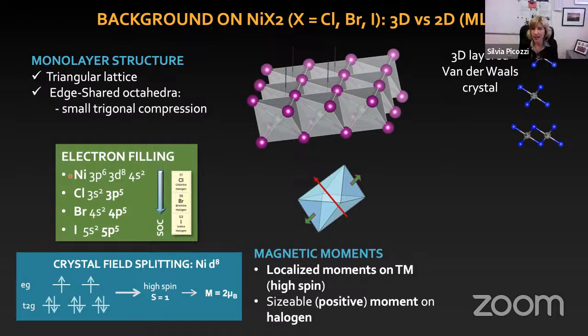And so nickel is d8, and I have an octahedral crystal field, so I have the t2g fully filled and the eg half filled. So I have 2 Bohr magnetons per nickel atom. And then if I move from nickel chloride to nickel bromide to nickel iodide, I'll see my spin-orbit coupling increases. So I expect larger spin-orbit coupling effects in iodide compared to chloride.